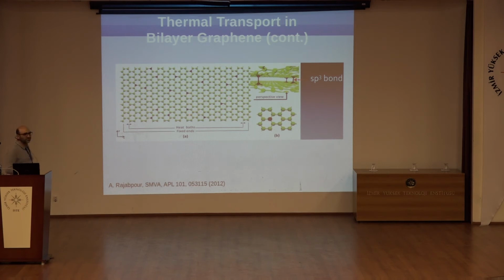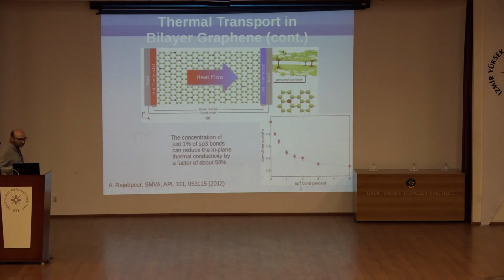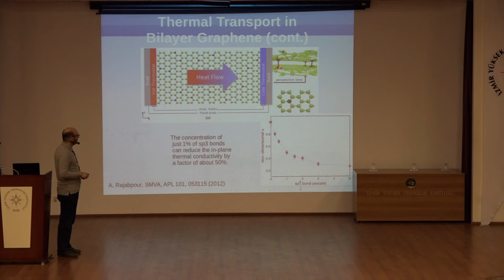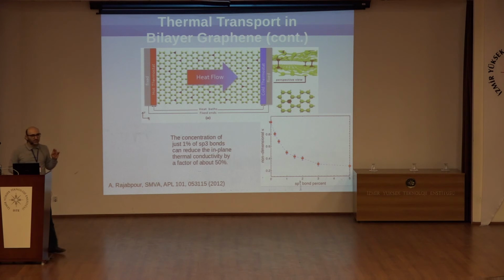There is another kind of tuning thermal conductivity, a non-reversible case, by creating sp3 bonds in, for instance, bilayer graphene. You know that the thermal conductivities of bilayer graphene and monolayer graphene are almost the same, but it is possible to get different thermal conductivity by creating sp3 bonds between the layers, and this is feasible by femtosecond laser pulse or electron beam for creating these sp3 bonds, and with 3% of sp3 bonds in bilayer graphene, it is possible to decrease the thermal conductivity of graphene by about 70%.